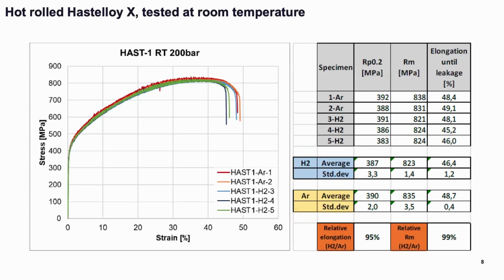So if we look at the results, maybe for many of you in the room these results will probably not be that surprising. For the hot rolled Hastelloy X, there is data in the literature. As long as you don't have huge hydrogen concentrations in the material, it should be rather insensitive to hydrogen embrittlement. And here we see very small differences between the hydrogen and the argon tested material, both when it comes to the strength and the ductility.